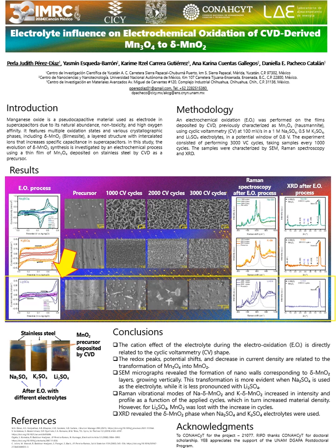no further nanowall formation occurs. Raman spectra at 1000 cycles show the characteristic bands of lithium birnessite, but these bands diminish by 2000 cycles and disappear by the end of the process. Consequently, X-ray diffraction does not show any peaks for birnessite.